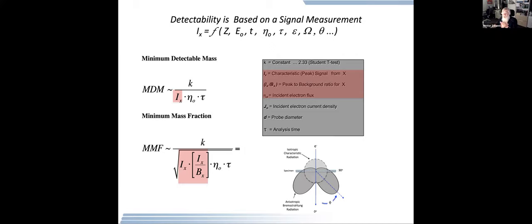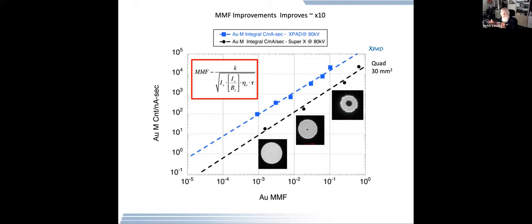And I remember what I'm interested in is maximizing the intensity in terms of the minimum detectable mass, or in terms of minimum mass fraction, maximizing the intensity times the peak to background ratio. Both of these are important parameters. They depend very strongly upon the samples you're looking at and the geometries. Let me just give you an example of the improvement of minimum detectable mass now.